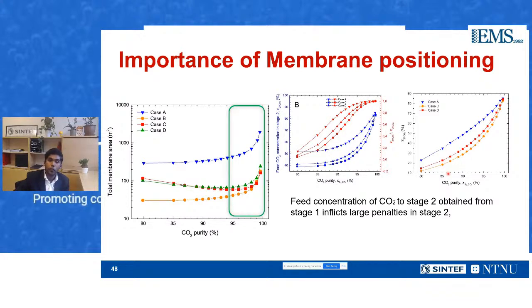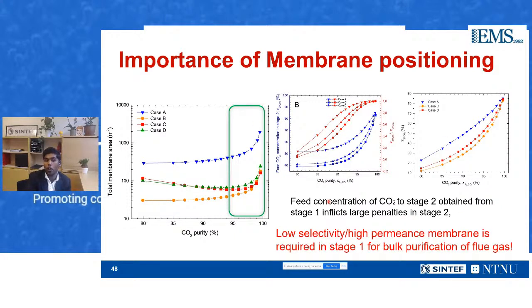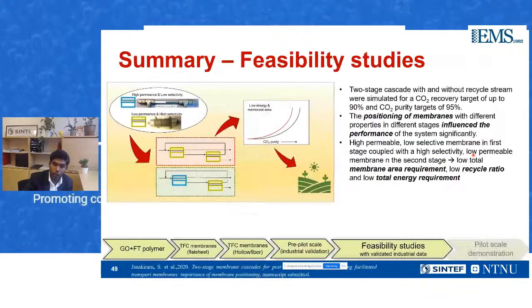So which means the feed concentration of CO2 to stage 2 obtained from stage 1 inflicts large penalties. So you don't want a high selectivity membrane in the first stage, because you want a low selectivity and high permeance membrane in the first stage, so that there is a bulk purification of the flue gas, so that there is no penalty on the second stage, which means the second stage operates at a much lower average driving force.